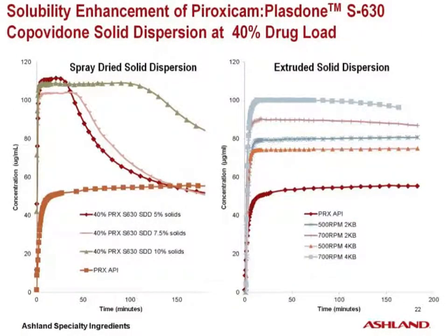Here are the dissolution profiles of the 40% drug load solid dispersion. Once again, spray-dried solid dispersion produced with high solution concentration showed lower crystallization tendency and better maintenance of supersaturation. For the melt extruded samples, dissolution performance was impacted by process conditions. The sample generated under higher screw speed with more kneading blocks showed the most significant dissolution enhancement.